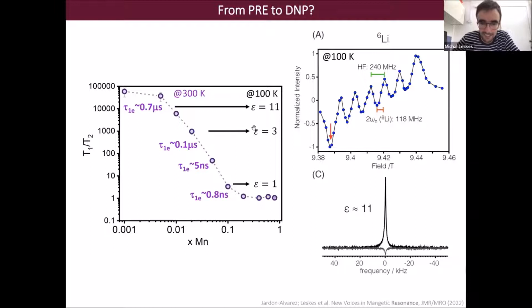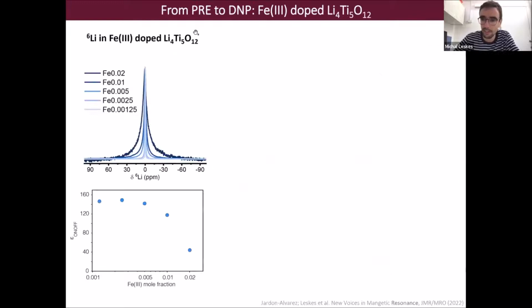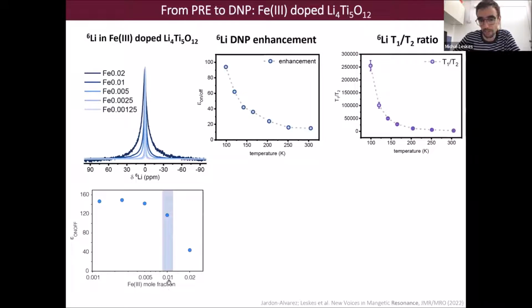But we wanted to see if we can get a little bit more quantitative with this approach. And for that, the starting point of 11 seemed to be not enough enhancement to do a more quantitative study. So we went back to another sample, the lithium titanium oxide that I presented already before, which we doped with iron 3+. And here, even for lithium-6, we are able to get large enhancements of above 100. So we took one of these samples, with an iron concentration of 0.01 moles, and measured the DNP enhancement as a function of the temperature at which we were performing the measurement.